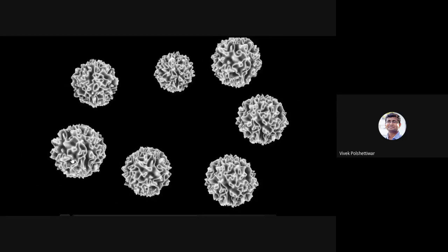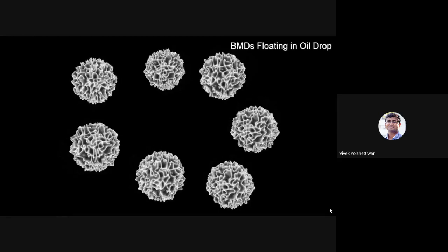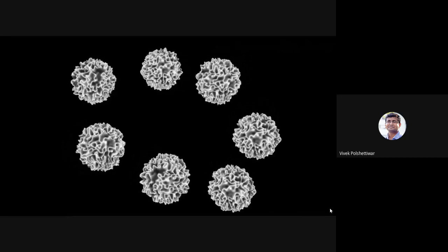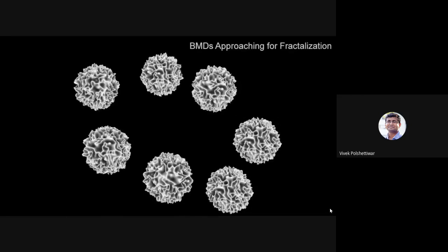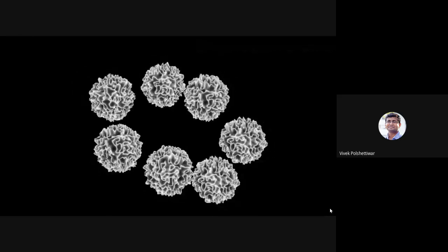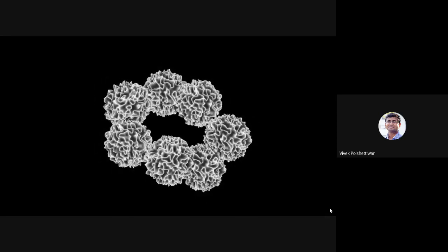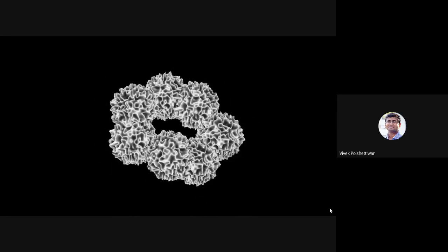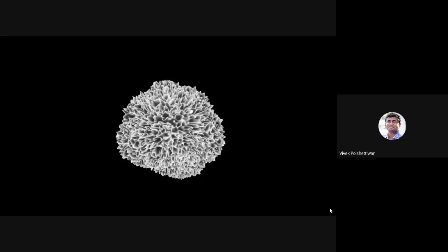Now, we learned how to keep them away from each other. If we keep them away from each other, I get smaller DFNS nanoparticles. I can merge 3 of them, 4 of them, and I get different sizes of the particle. In fact, I can merge all of them together, and I get a bigger droplet. And that allows me to then produce DFNS of even bigger size. So that's how we learned how to make nanoparticles of different sizes as well as different fiber density.